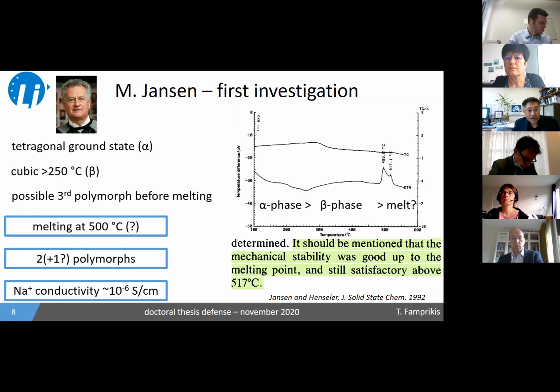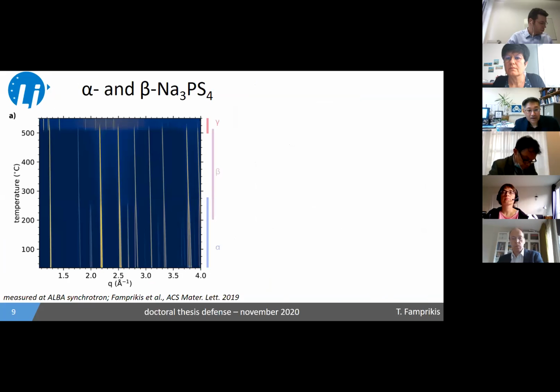Just to drive the structure home, I'm showing here a series of diffractograms that were taken with temperature on the y-axis. So basically each line here represents a diffractogram. The yellow highlights the Bragg peaks. You can see very well that we have a single phase up to about 250 C, and then some characteristic peak merging and peak extinctions that are characteristic of a second order transition from the alpha to the beta phase.